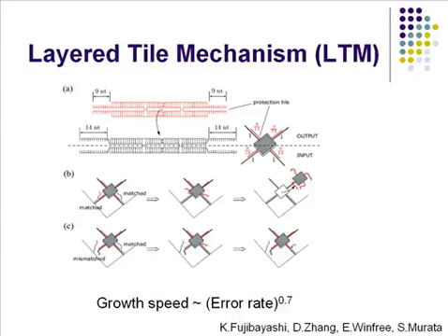Then it is dissociated from the tile. The dissociation opens the next output strands, which allows the next association of the tile to the adjacent lattice point. And when this tile has a mismatch, then one side of the covering tile can be removed, but it's not enough to remove all of it.